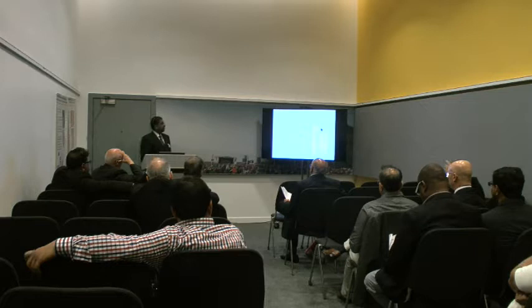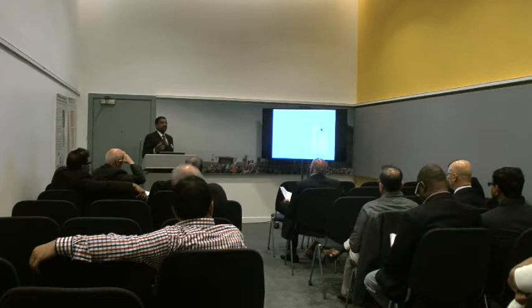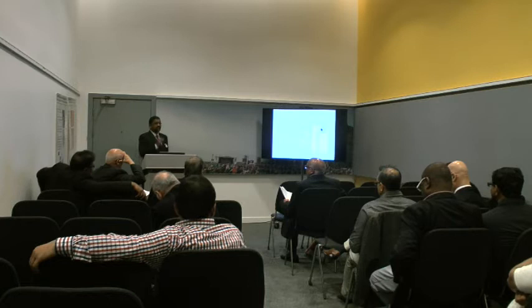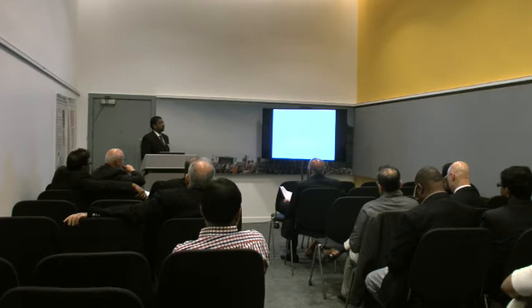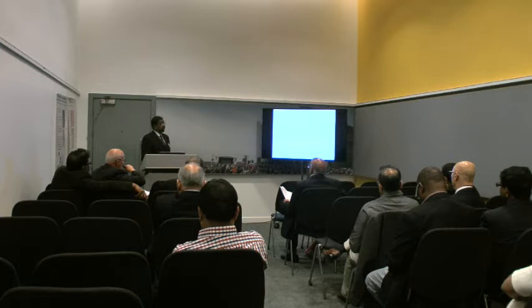Now, Stryker has made X3 polyethylene. The X3 is called that because it's a triple annealed process, whereby it produces highly cross-linked chains. And in that measure, when it's been used for 40 millimeter heads against a 50 or 52 millimeter acetabular shell, the thickness of the polyethylene is only 3.8 millimeters. Now, I could not find any other polyethylene which is as thin as that. The X3 liner is an ultra-high molecular weight polyethylene, but the new annealing process is, you irradiate and heat it to a sub-melting temperature three times, so that it produces cross-linked chains. So the fatigue strength is better, and the wear, but the important thing is, the surface wear property is much, much better than a conventional polyethylene.